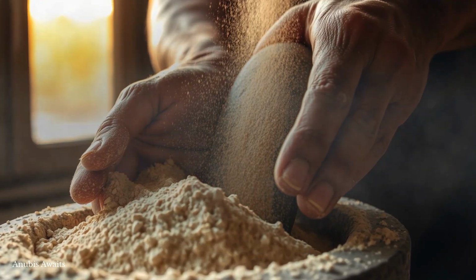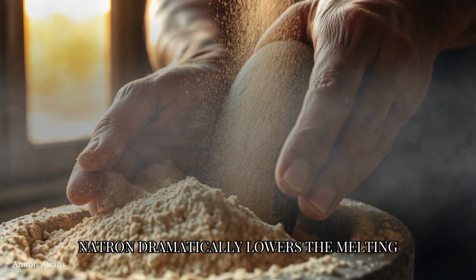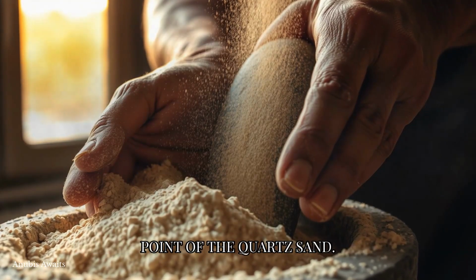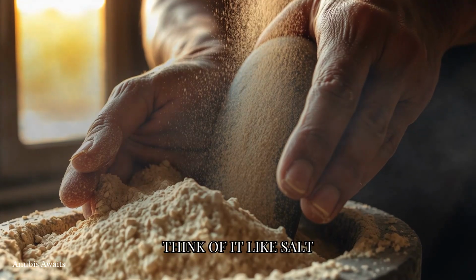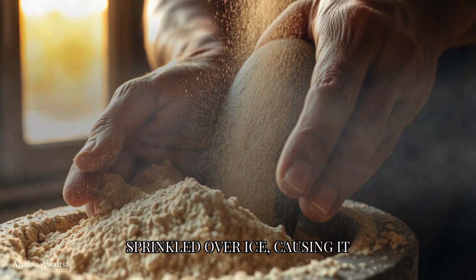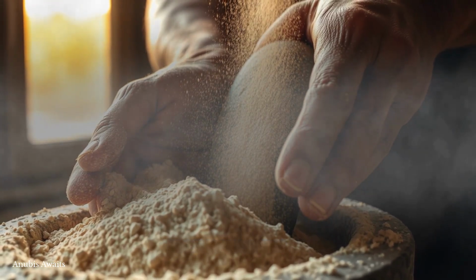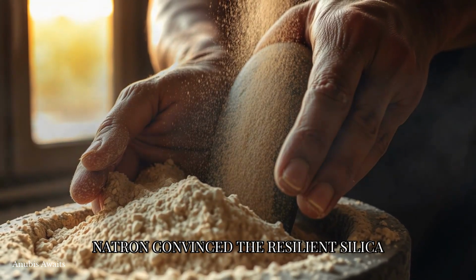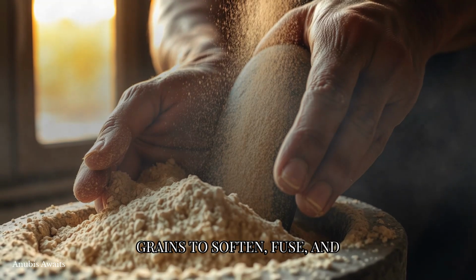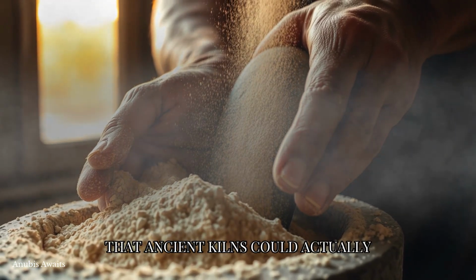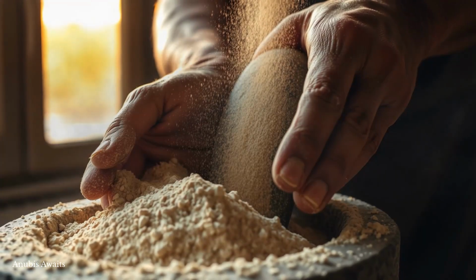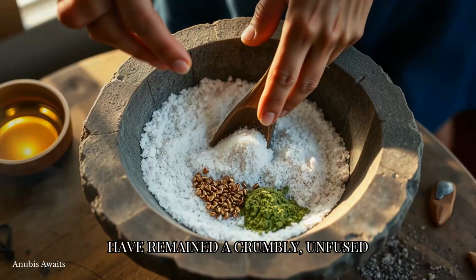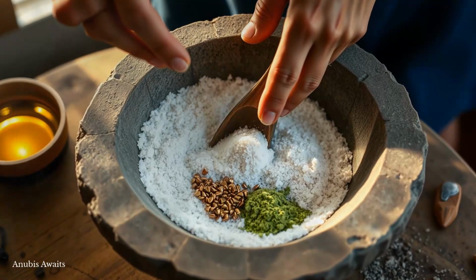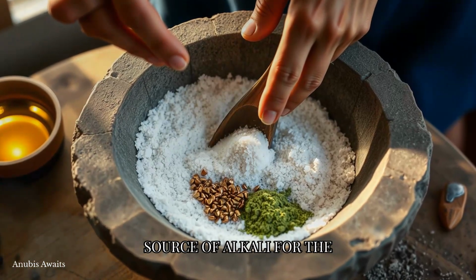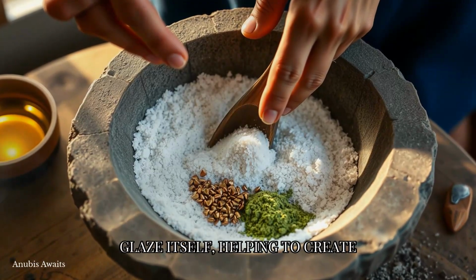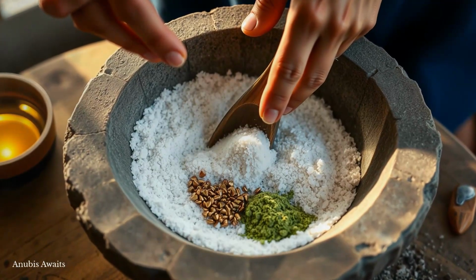First, it acted as a flux. When heated, the soda in natron dramatically lowers the melting point of the quartz sand. Think of it like salt sprinkled over ice, causing it to melt at a colder temperature. Natron convinced the resilient silica grains to soften, fuse, and bond together at a heat that ancient kilns could actually achieve. Without it, the sand would have remained a crumbly, unfused powder. Second, natron was a vital source of alkali for the glaze itself, helping to create that signature glassy surface.